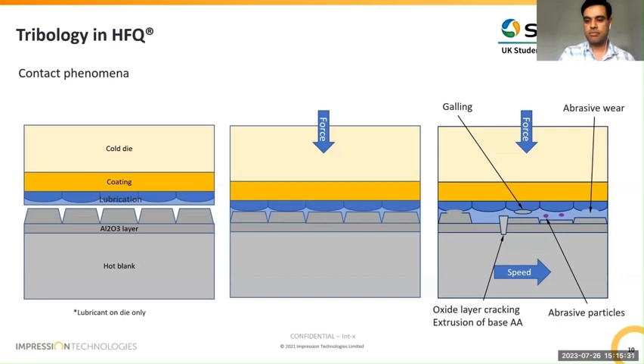So an entire contact is evolving as we are forming. And at the same time, the blank is cooling and the die is gaining temperature. So again, the temperature exchange also affects the rheological properties of the lubricant, which in turn changes what is happening at the contact. And all of this is happening within less than 1 second.